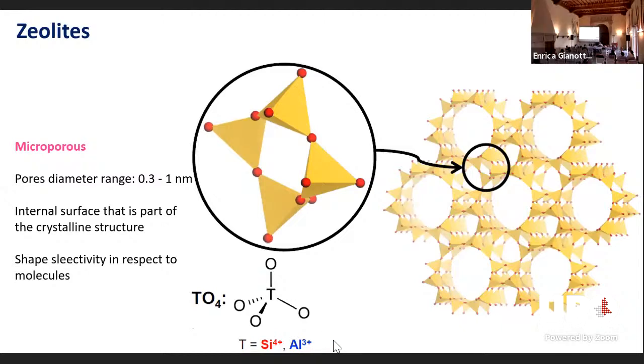So starting from zeolites, the building block is the simple tetrahedron, and through the link of the oxygen, we have the possibility to make different networks. And the properties are related to porosity, which are in the range of 0.3 to 1 nanometers. So normally we consider these molecular sieves. And so big molecules cannot enter inside the pores of these materials. And we have the shape selectivity. And sometimes we need to change the dimension of the pores with some treatment. And I think that this was part of the work that was developed in your project.